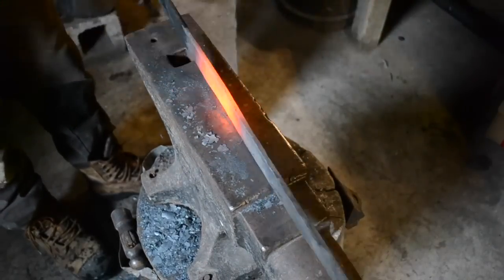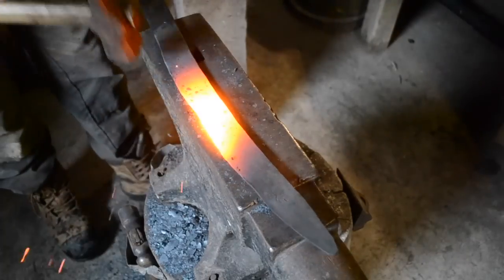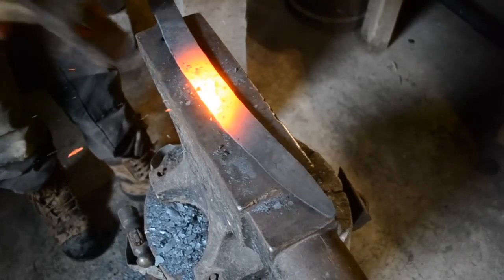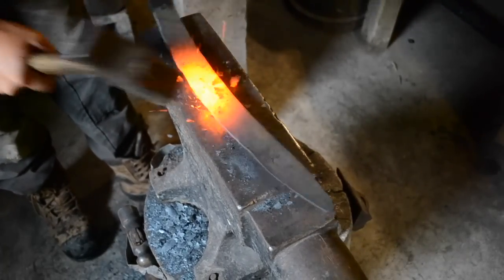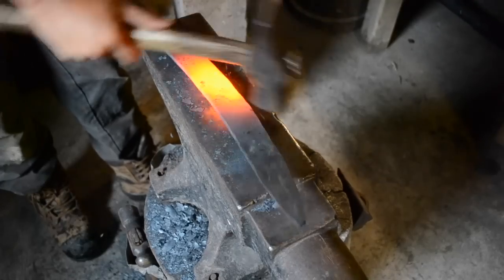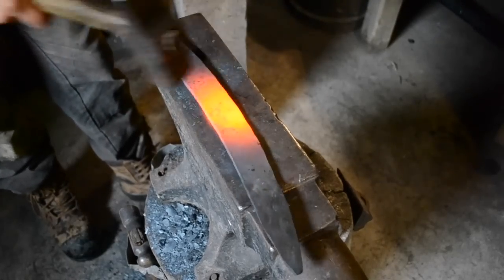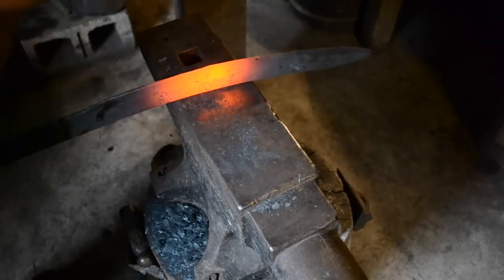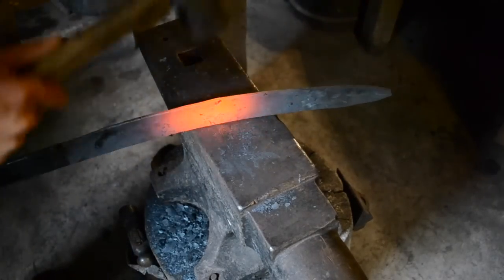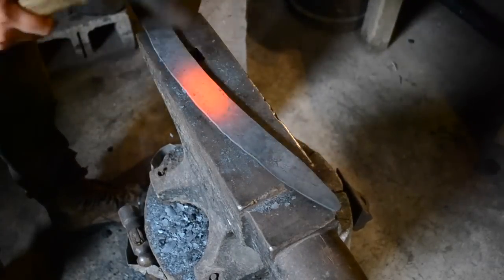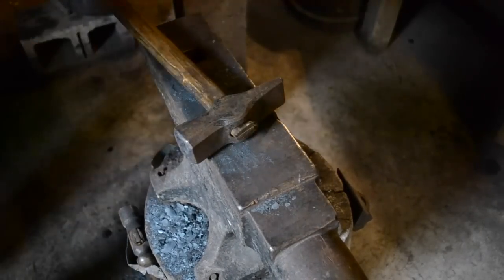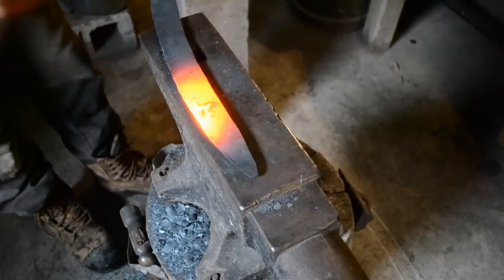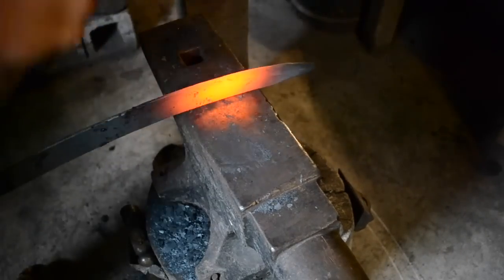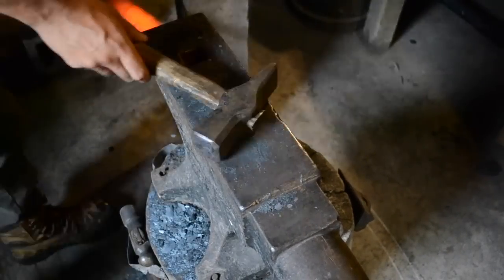You can see which parts of the edge are still thicker because the blade won't be quite as wide there. You want the blade to be an even width all the way down. The sword is also starting to curve from the edge being stretched more than the spine. It's starting to curve a little bit too much, so we're going to pound it a little bit flatter. The curvature is just going to keep increasing as you work down into the unforged section, so you want to be a little bit conservative, always straightening it out.